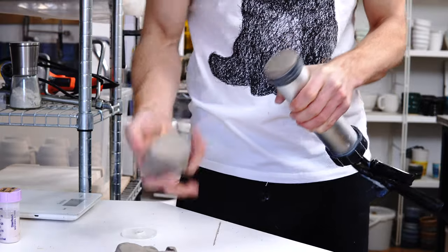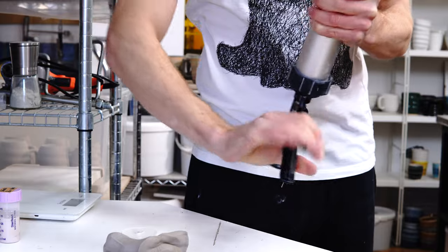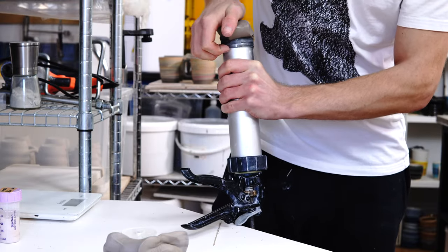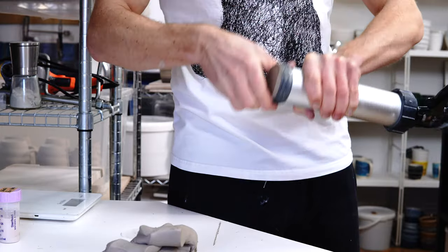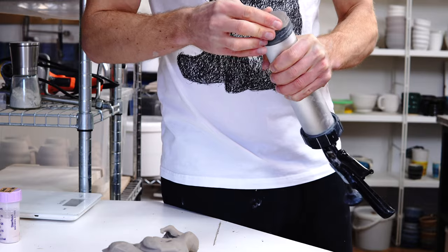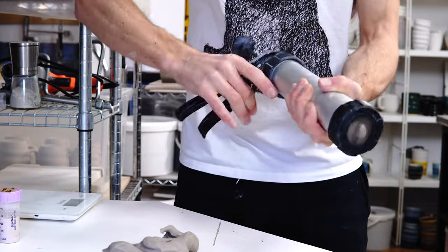With the plunger fully plunged, I use the pressure of the clay to force the plunger down. It doesn't really want to slide — particularly once there's a bit of clay in there — so you've got to put a decent amount of force in. This way forces the clay in under enough pressure that no air in theory can come in with it. Once I've pushed the clay in, I then pull the trigger once to pop it back out and round the top of it off. I round the ball of clay that I'm loading into it to make sure that there's no air trapped between the two of them, and then I press down to squash the clay in and push the plunger down. That's pretty much it — once you get the hang of that, it doesn't take too long to load and should more or less avoid any air bubbles.